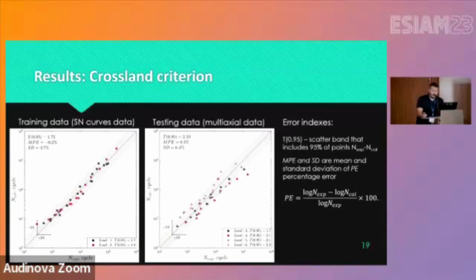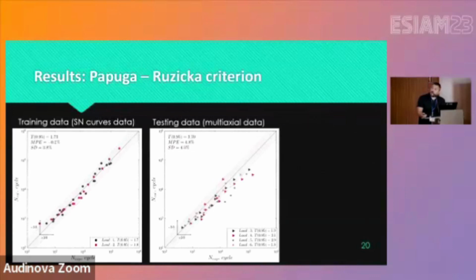So the Crossland, which was quite surprising, did quite well here, and very good for the third loading data. So one of the in-phase multi-axial tests, not so good for the other. It's 3.1, and very good for the out-of-phase multi-axial fatigues, but because it's like only 2.3 the scatters here, which I will explain later why. On the other hand, the Papuga-Růžička criterion didn't work so good, maybe except for the first one. The fifth and the fourth one, this one was very close to 4. The scatter was up to 3.9, and for the load 4, it was 3.1.